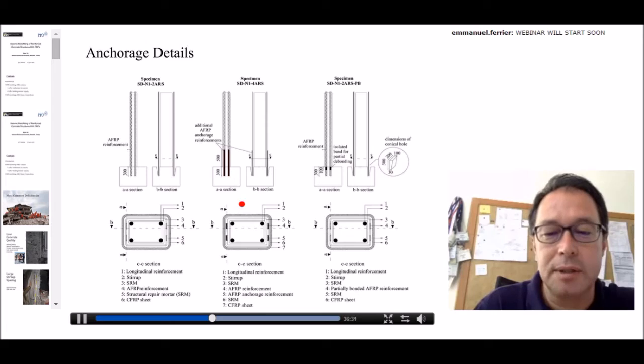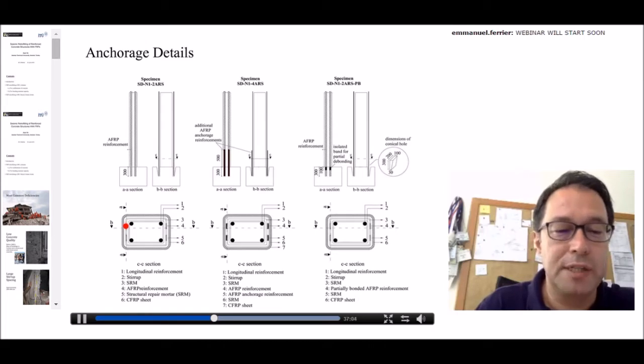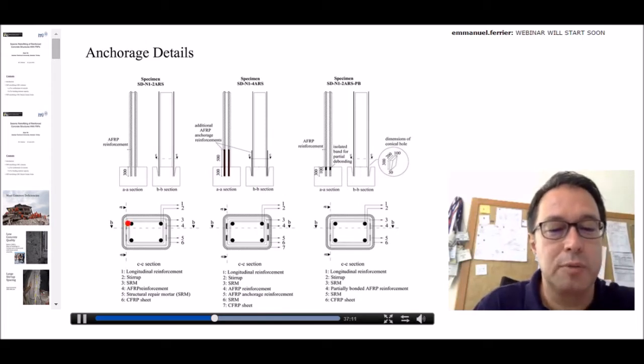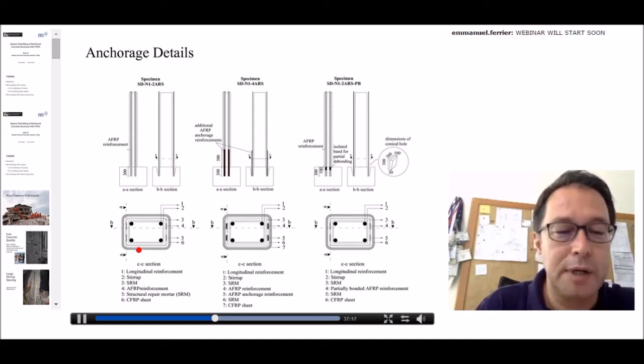Other than these details, the retrofitting scheme is similar. But I should say that, of course, that's a different technique because, as I'm going to show in coming slides, what we did first before applying this technique is to remove the cover concrete. We just broke the concrete because you know that these are poor quality specimens. Therefore, the concrete is poor quality. Then it's not a big work to remove this poor concrete, because if you don't have a good concrete here, then debonding of these AFRP bars would be inevitable because of the poor strength of concrete. Even though you use very high quality epoxies or whatever you like, since the concrete quality is poor, the concrete would be delaminated from the cover itself.